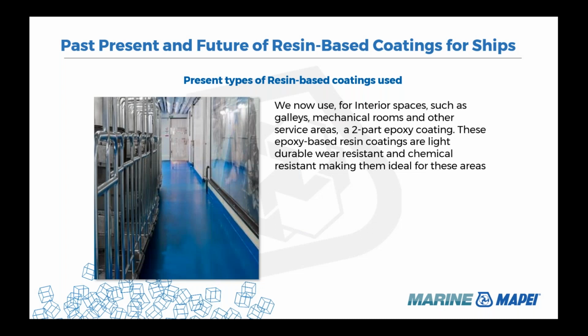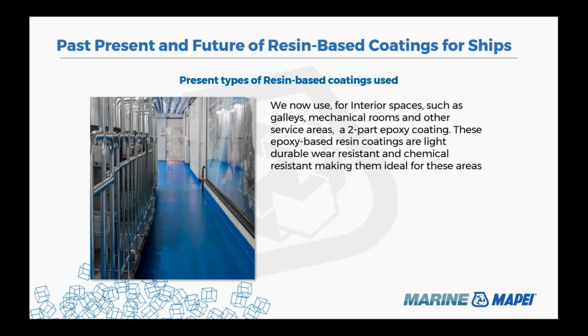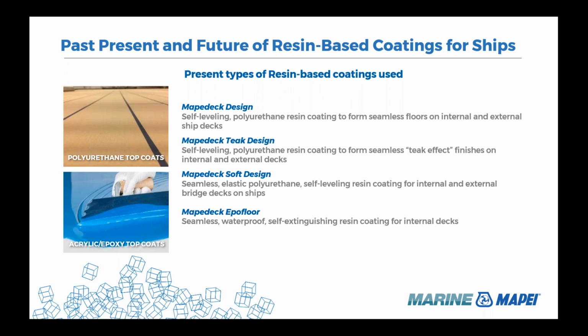The epoxy resins are being used primarily in galleys, mechanical rooms, garbage rooms, and other service areas on the ships. These are two-part epoxy coatings, and they're light, durable, and wear resistant, as well as chemical resistant, making them ideal for the service areas of the ship. And because they're not exposed to ultraviolet radiation, we don't deal with issues with yellowing. MAPEI's present use of resin-based coatings on ships includes an aliphatic polyurethane resin-based flooring for open decks, and the epoxy-based flooring for internal areas of the cruise ship applications.